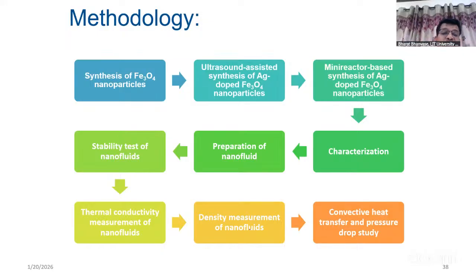These formed Fe3O4 nanoparticles were dispersed in the reaction medium, and then AgNO3 is added, and then sodium borohydride - that will lead to the Ag-doped Fe3O4 nanoparticle. Its characterization is done by XRD, FTIR, and other techniques.